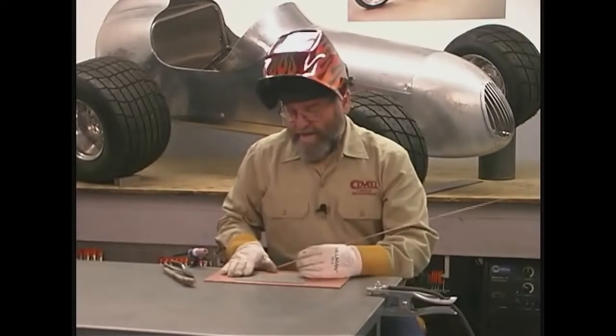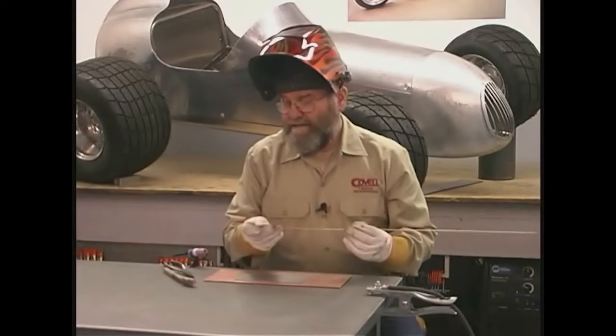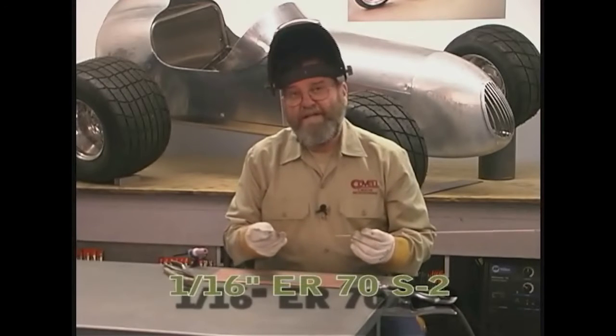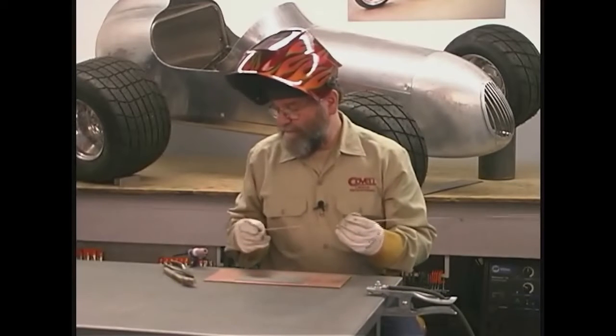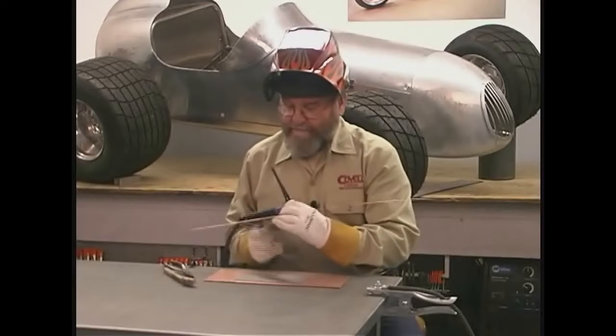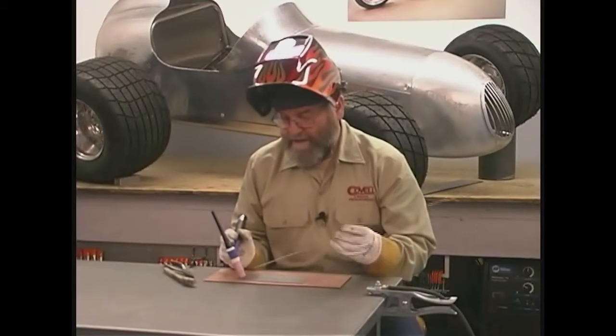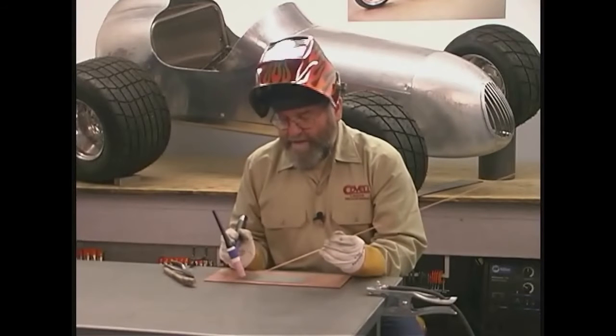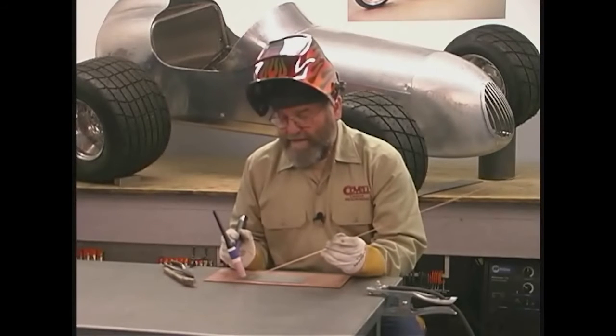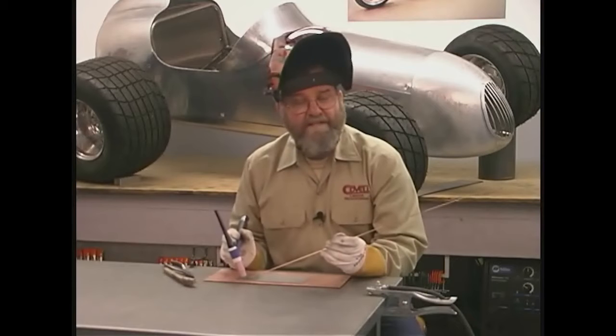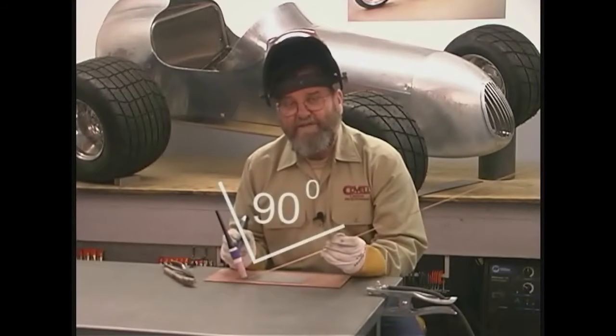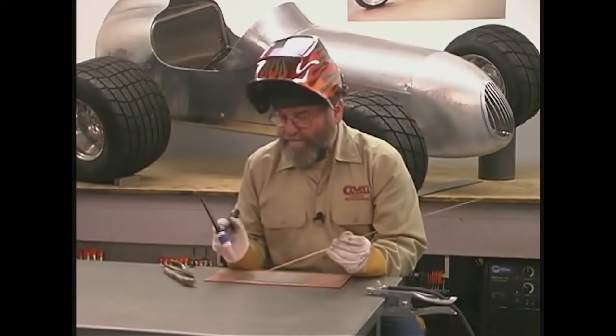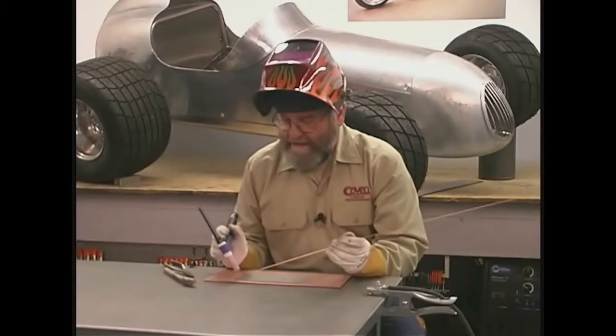Okay, so I've cleaned the next piece we're going to weld on, and this time I'm adding filler rod. This is 1/16 inch diameter ER70S2 welding rod. The machine settings are the same. Just like before, we'll hold the torch at a 15 degree angle in the direction of motion. I'm going to hold the rod at about a 15-degree angle from the base metal. So you'll see the angle between the rod and the torch is just about 90 degrees. We'll get a little pre-flow going from the torch and then start the weld.